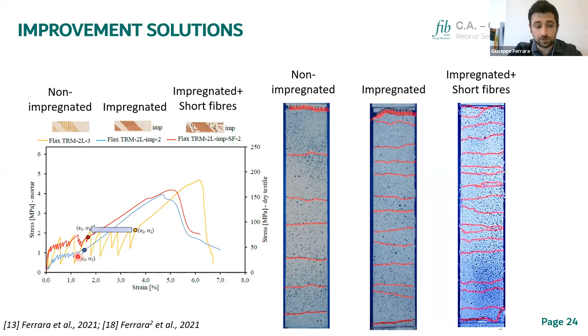And also, if you look at the drops of the load due to the opening of the cracks, this is much lower with respect to the reference series. And also, if we compare, once we increase the tensile strength of the mortar by adding short fibers, we also increase the normal stress in this phase